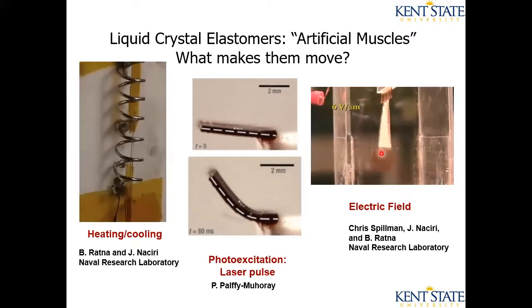The one on the right here, these two actually are both experiments that were made at the Naval Research Laboratory in Washington, D.C. The liquid crystal elastomer here is this little piece of tape, like a little film. It has a little weight hanging from it at the bottom, and it's attached at the top. On the front and back, it has some conducting grease, which is used to create a capacitor. You apply a voltage across this little film, and when you turn the voltage positive, it twists in one direction, and you turn the voltage negative, and it twists in the other direction. The one in the middle, unfortunately, I don't have a movie for, but this is a little piece of polymer in the shape of a diving board. This experiment was done at Kent State by my colleague, Peter Palffy-Muhoray, and he shines a little photo pulse on the top, and it pops up. It pops upward, right? So it also moves.